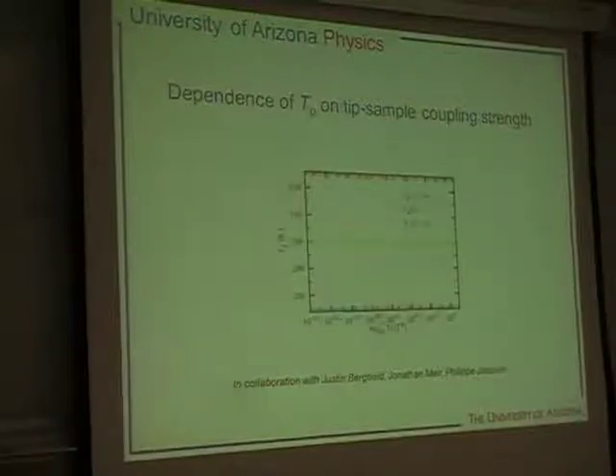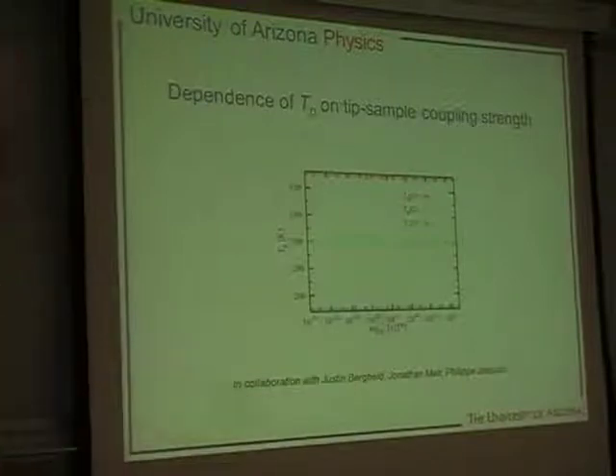And it does not. So if you see here, I've changed the trace of the gamma p, what I call the tunneling width matrix that describes the tunneling of electrons from the apex atom of that platinum tip into the sample. There's a matrix describing that tunneling, and I've here taken the trace of this matrix, and over like 12 decades, the temperature is basically completely independent of the value of that coupling.